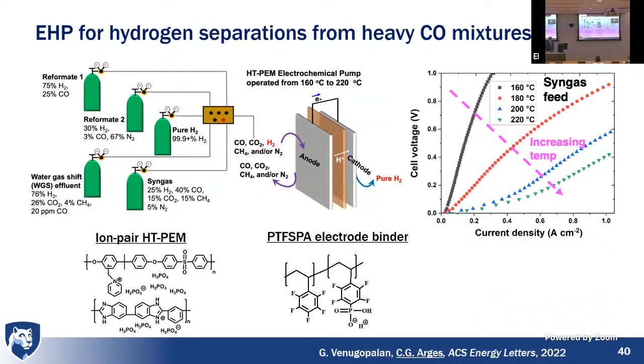All right, so I want to tell you about purifying hydrogen from CO gas streams, and we're going to use our best binder. We have another binder I'll tell you about quickly again. At that time, last year, this was our best binder in our membrane. And we can feed in syngas, which has 40% CO in our gas stream with 25% hydrogen. And we can feed in other gas streams that are reformed hydrocarbons with lower CO content.